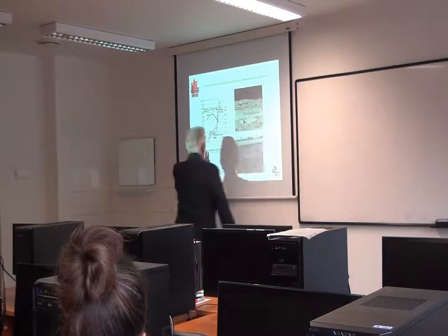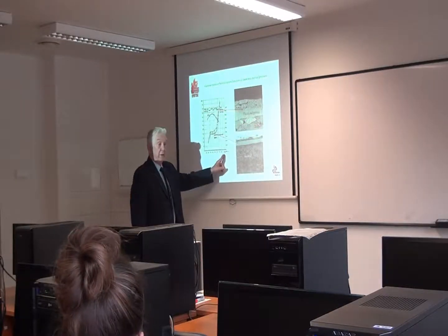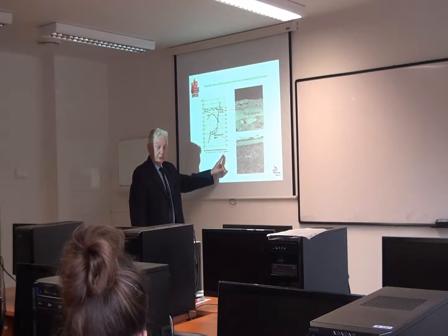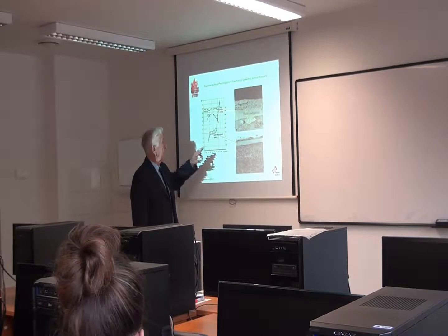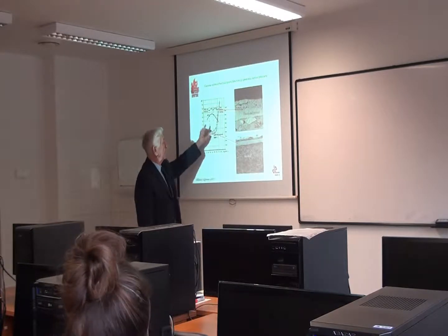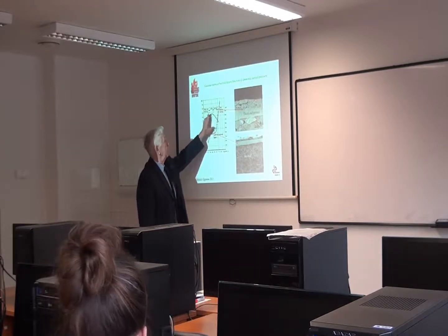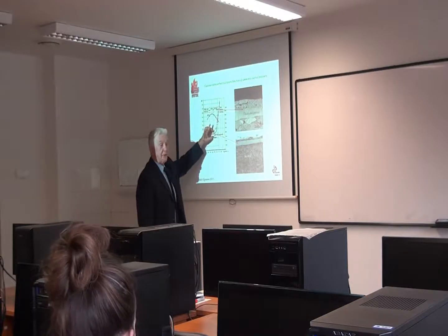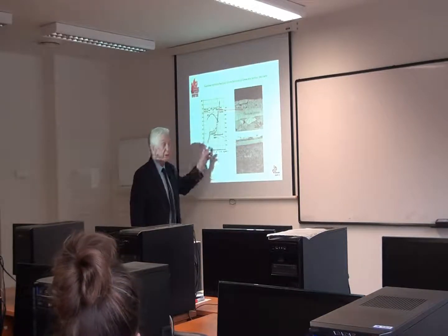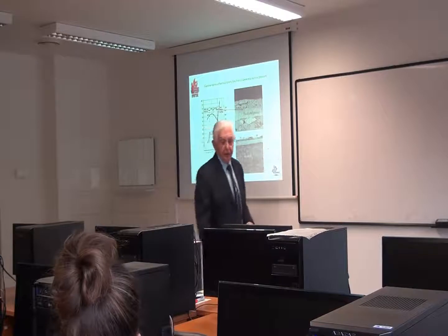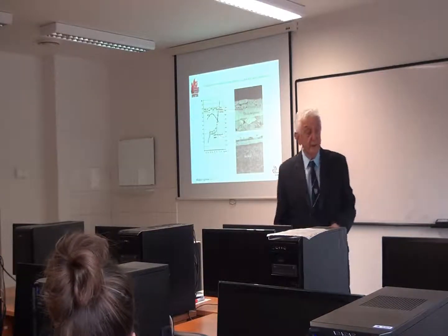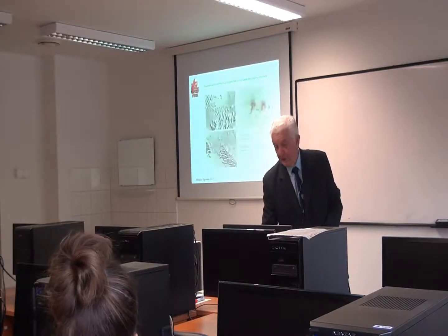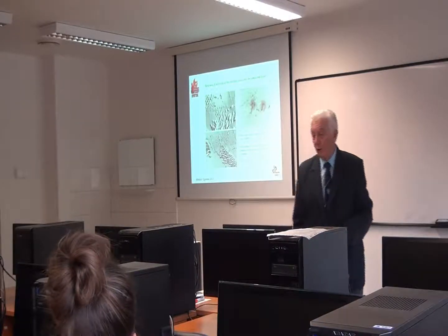You see, if we control in the process the ammonia partial pressure, then we can obtain a region where we have high hardness, we have a stable layer and no porosity. This is an important diagram. So I told you that I do not enter into the technological details because I wanted to give you an idea what is and what for.